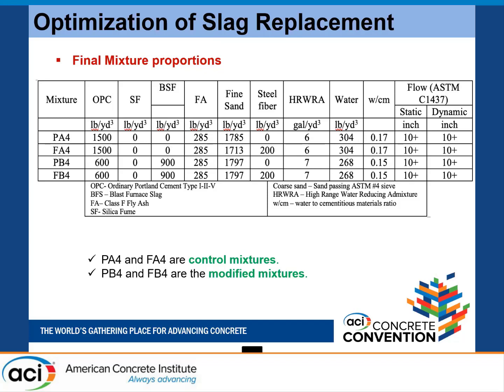The basic difference between series A and series B is that series A is with no slag, series B is with slag. In series B, we have used just 600 pounds per cubic yard of cement. That is just a conventional concrete level of cement dosage. The cement factor is very, very low. And we used 900 pounds per cubic yard of slag. So 40% cement, 60% slag in a UHPC system. And in all of these 4 mixes, with slag and without slag, the flow on a spread table is greater than 10 inches, which is way more than enough for bridge applications.